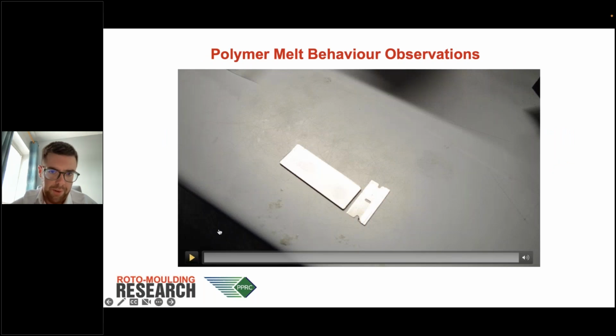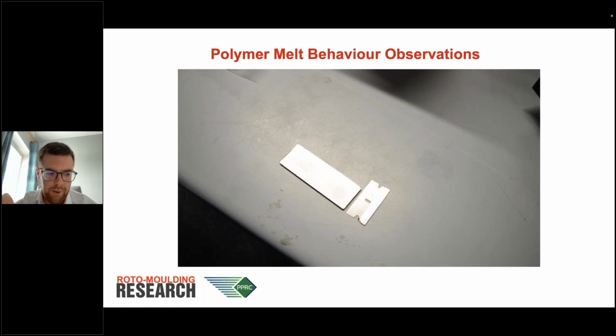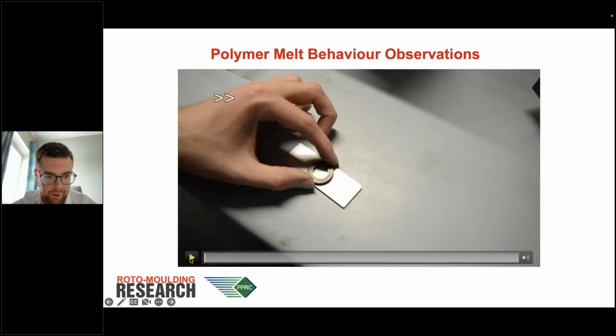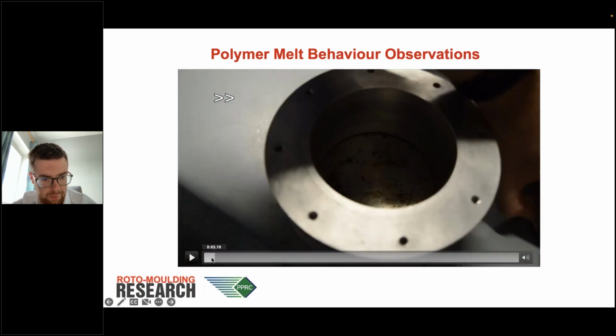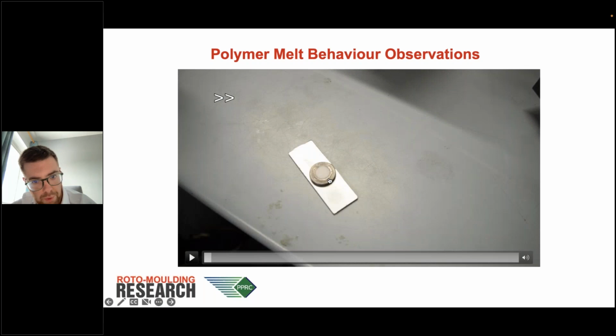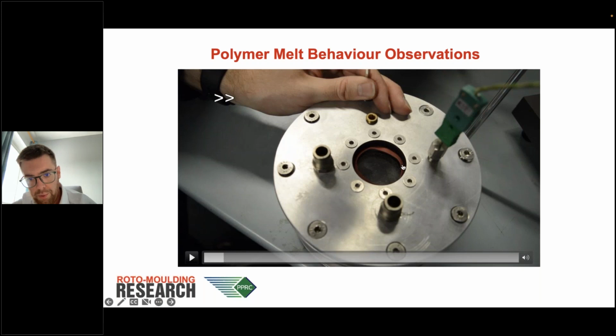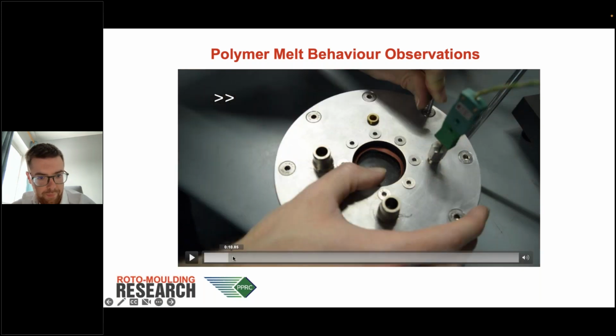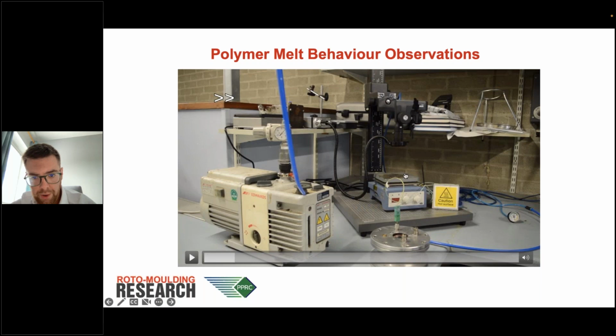So at the same time as doing that, it became obvious that there was a relationship between the sintering and densification behavior, the bubbles that are trapped within the polymer melt itself. So I developed an experiment where I have a glass plate and a little jig to put the polymer powder into. So that little jig is filled with a polymer powder, and the jig is then removed. That plate is then placed inside this contraption with a glass viewing window, and the little polymer powder plate is in the bottom of this chamber. That then gets set up on this hot plate over here.